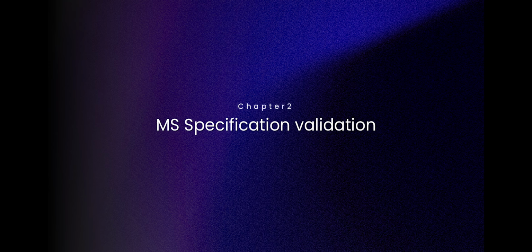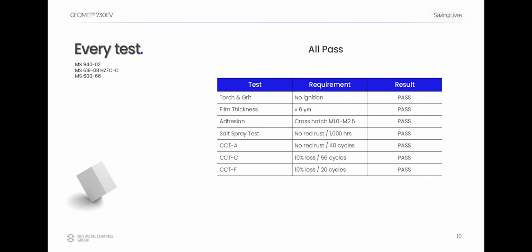Next, let's move from mechanism to validation. For automotive use, a good mechanism is not enough. The product must pass the required specifications. GeoMet 730EV passed all key requirements: Torch and grit, pass. Film thickness, pass. Adhesion, pass. Salt spray test, pass. CCTA, CCTC, and CCTF, all pass. This means GeoMet 730EV is not only fire resistant, it also provides corrosion protection, it has good adhesion, and it is ready for mass production.